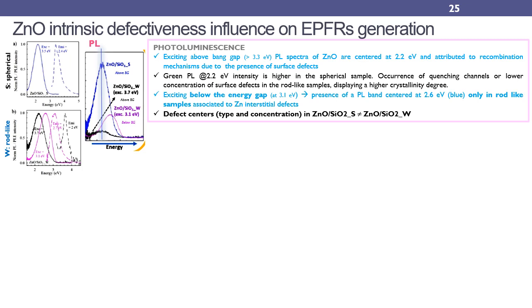The same green band is seen also in the zinc oxide grown on rod-like silica supports, but with a weaker intensity. The weaker intensity may be due to the presence of quenching channels in these samples and to a lower concentration of surface defects. Indeed, the zinc oxide nanoparticles attached on rod-like silica are characterized by a higher crystallinity degree.